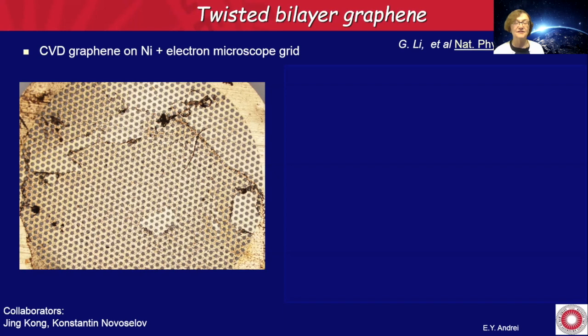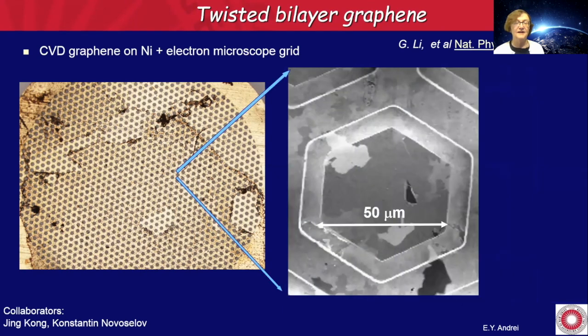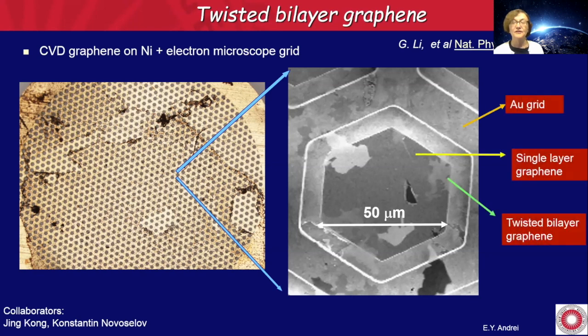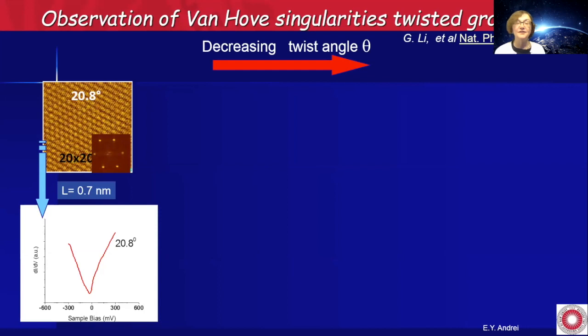Now, if you zoom into this electron microscope grid, you see these holes where you have suspended graphene, and here is the gold grid. Here we have a single layer graphene, and then it turns out that inadvertently this was not a monolayer graphene, but contained many twisted bilayers with any twist angle that you could have imagined. At the time, we had no idea that this was going to be very interesting, but looking at it, we had many surprises. We measured one such twisted layer, and you can tell the twist angle just by looking at the period of the Moiré pattern, or at its Fourier transform, and immediately you can get out the twist angle, and then you look at the density of states.